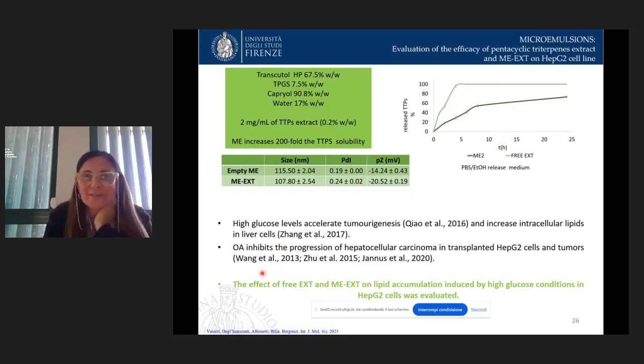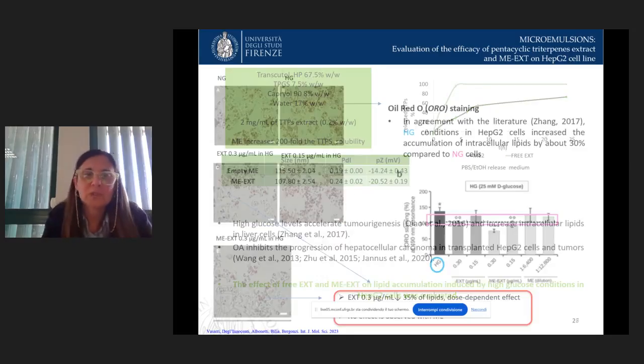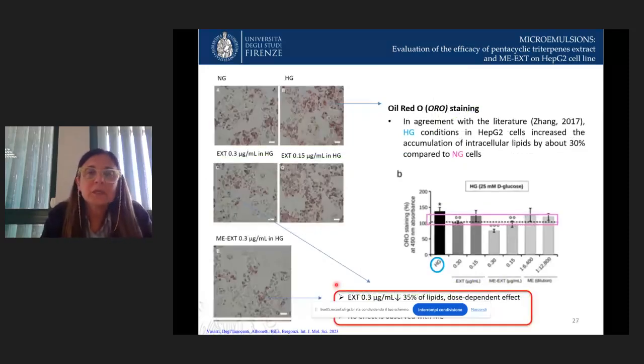Then we wanted to test the efficacy of the extract that contains oleanolic acid but also other terpenes, and also the effect of the extract loaded in microemulsion. We monitored the effect of these two samples on lipid accumulation in the hepatocellular model. We treated the cells with a high amount of glucose, as reported in the literature, and we observed an increase in the production of lipid inside the cells. The lipid accumulation was evidenced by a colorimetric method, the Oil Red O method.